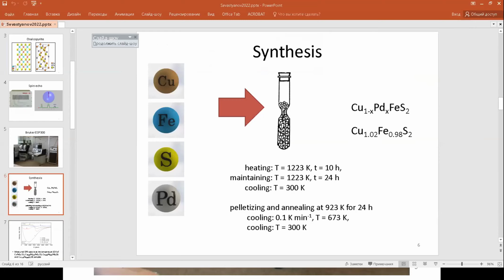Polycrystalline samples with a nominal composition of undoped chalcopyrite and palladium doped chalcopyrite were synthesized from a mixture of pure elements obtained from Sigma-Aldrich, including copper, palladium, iron, and sulfur. The synthesis of the polycrystalline products was performed in evacuated and sealed quartz ampoules.